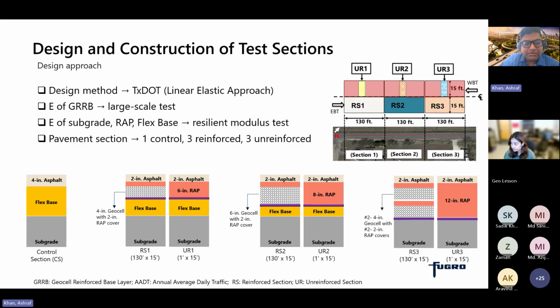And if you look at the naming, we have RS1, RS2, and RS3, which are Geocell reinforced section with 6 inch, 8 inch, and 12 inch of Geocell reinforced RAP base layers. And on the westbound side of the pavement, we had 3 unreinforced section, which are UR1, UR2, and UR3, which had 6 inch, 8 inch, and 12 inch of RAP base layer without any reinforcement. So we have one control section, three reinforced section, and three unreinforced section to check the performance in the field. And we varied the geocell reinforced section thickness from 6, 8, and 12 inch to see with the increase of thickness of geocell reinforcement how it is improving the performance.